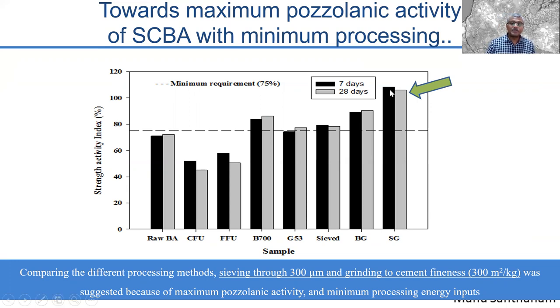So when you just sieve and grind, you get a pozzolanic activity that is more than 100%, indicating that you nearly get cement-like performance with up to 20% of cement replaced by bagasse ash. And that's really a tremendous performance that you can expect for processed bagasse ash.